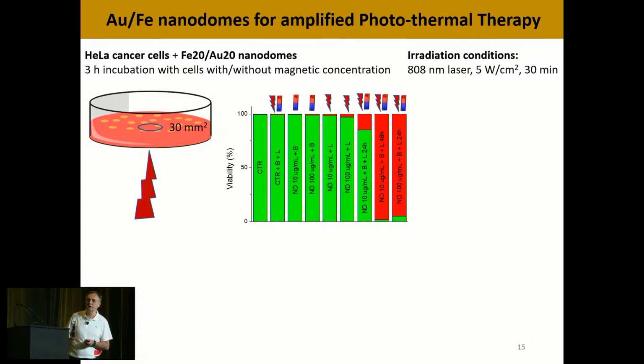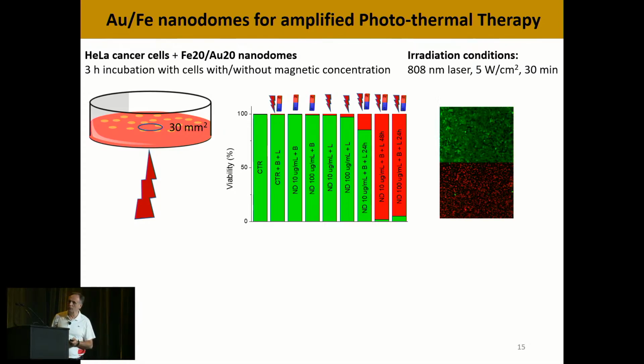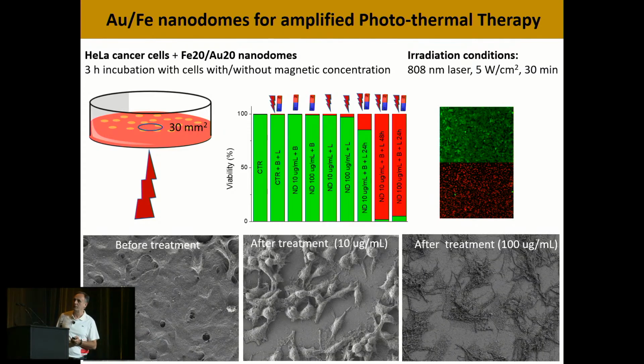So to understand what was happening, this is the cell counting. Before, in green, all the cells are alive. After the laser, all the cells are dead. But then we did an SEM of the cells. This is before treatment, this is the treatment with 10 micrograms per milliliter, and this is the treatment with 100 micrograms per milliliter. You see here that when we use 100 micrograms per milliliter with the laser and the magnet, we literally fry the cells. This is not good because these cells have died by necrosis. Necrosis is bad because it has bad side effects on the healthy cells.